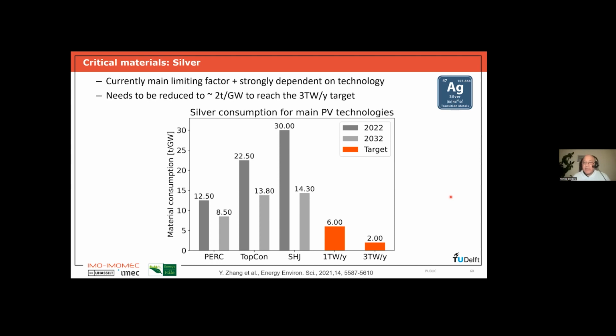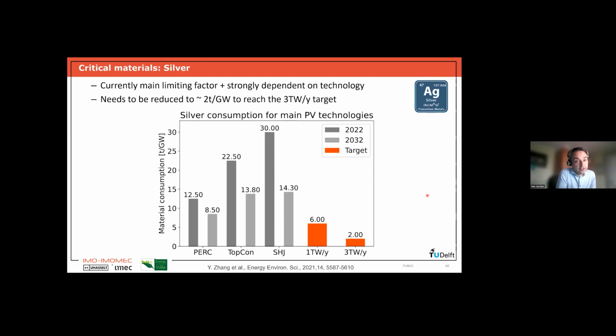Okay, the side Qassu asked about the EVA, ethylene vinyl acetate, encapsulation, if it's good for a perovskite solar cell. Yeah, I have to say that EVA is also used less today for silicon than in the past. There are lots of alternatives being developed, because even in silicon we sometimes have problems with EVA, like discoloration. I'm not an expert on the encapsulation of perovskite solar cells. I know that at the moment we still haven't found the right material to properly do it. So probably it's not going to be EVA, but I cannot really say because I don't know what in the end it will be.